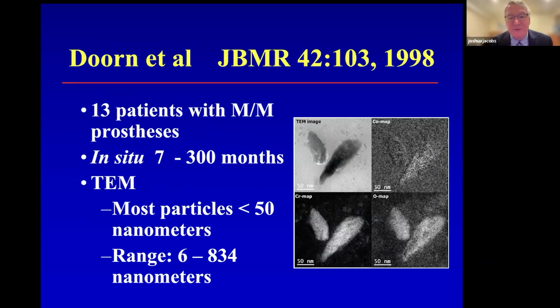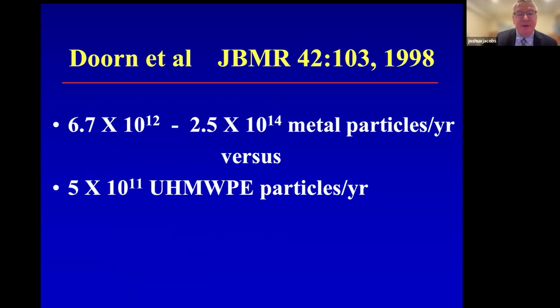One of the things we learned when we looked at tissue that was retrieved from individuals who had metal-on-metal bearings, some of them very successful, as you can see that some of these components were in situ for in excess of 20 years. If we look at the periprosthetic tissue and use transmission electron microscopy, we find that most of the particles are actually nanometer in size. There's a large size range. Most of the particles are less than 50 nanometers.